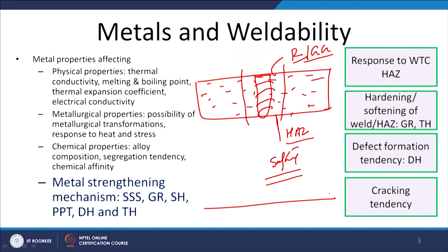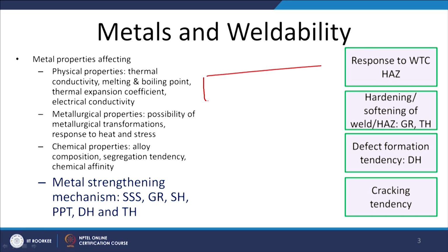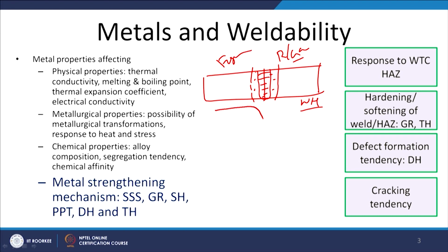And so, in case of the fusion welding of the work hardening materials, we may find a soft zone in the weld as well as the heat affected zone. The reason behind this is very simple: a work hardened metal, when subjected to fusion welding, loses all these effects, which are annihilated and vanish when the metal is brought to the molten state. Next to that, the zone also experiences softening due to the loss of the work hardening effect caused by recrystallization and grain growth in case of fusion welding, and because of this we may find that significant softening is taking place in the weld zone area in case of the work hardened metal.